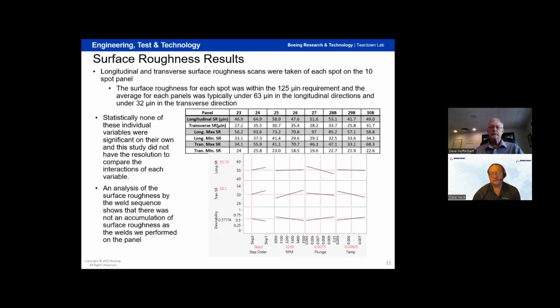And then running through the statistics, we didn't have enough panels to get interactions, but none of the variables we looked at really drove one way or the other for some of these surface roughness. So, if anything, we just saw that there was no buildup. So as we went, panel to panel, we didn't get heat buildup to cause extra surface roughness. So it was more good to see that it was not affected, but we could still get surface roughness that met what the blueprint requirements were.